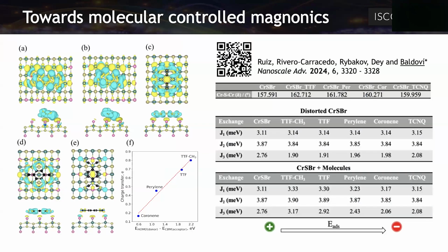This is the charge density. We observe here what I said before, that the molecule is tilted towards a bromide. Here, this means that in this case, it's a depletion of electron density that is going to the bromide here. And this is the case of the TTF, and this is the TTF with methyl, TTF-CH3, and this is the TTF. They're very similar, but in this case, it's even increasing the charge transfer. Then we have here the coronene, perylene, and the case of the acceptor, the TCNQ, that is almost just accepting a little bit, it is not performing any kind of change in the properties here.